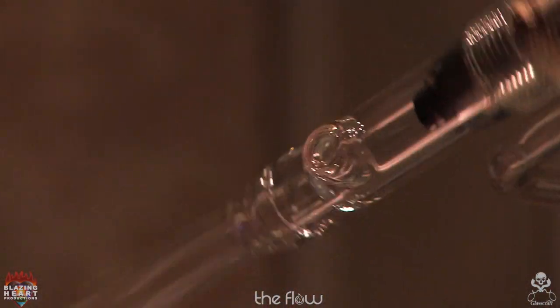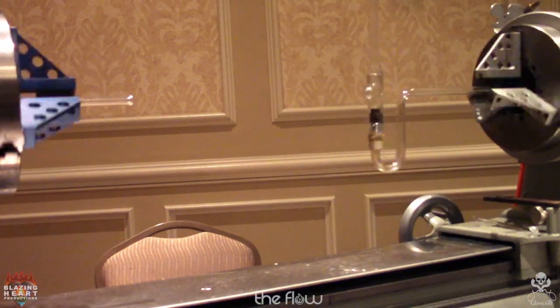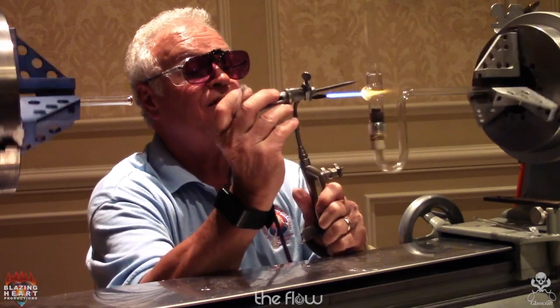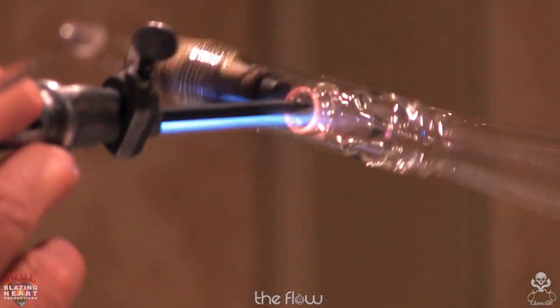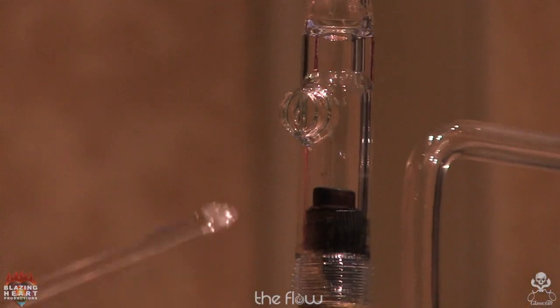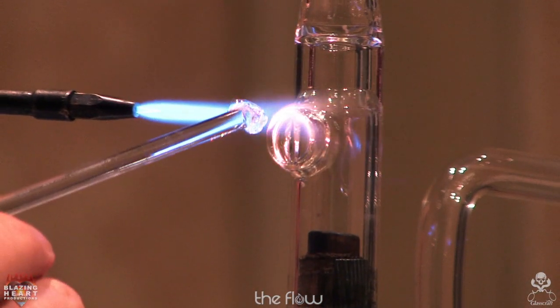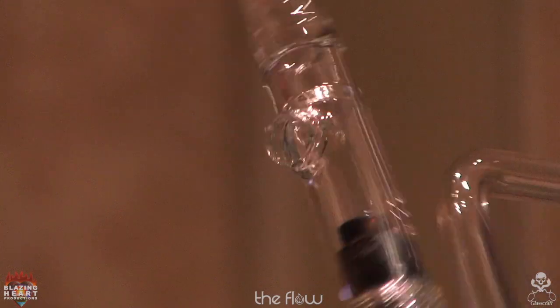Okay, again, you want to remove that little extra piece of nub glass that was at the end of the pull-off. A little softer flame so you don't starve it again from the sodium. Just pull that little piece out. Doesn't take long. It will make a world of difference in your end product.